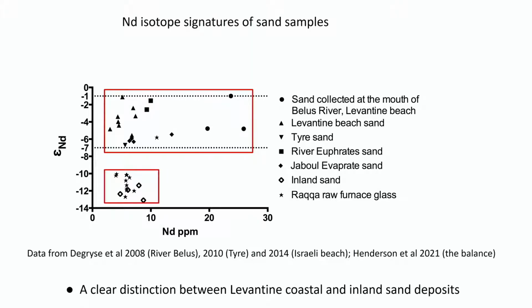And here are the neodymium isotope results for the sand signatures. And the key thing here is there's a clear distinction between Levantine coastal sand and inland sand deposits here. And we've also plotted the results of the Raqqa raw furnace glasses in that same field, and they correlate surprisingly well.